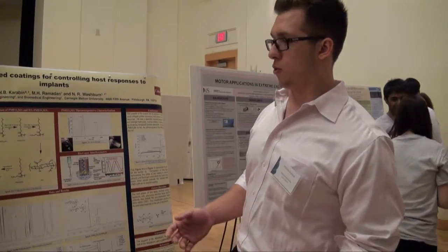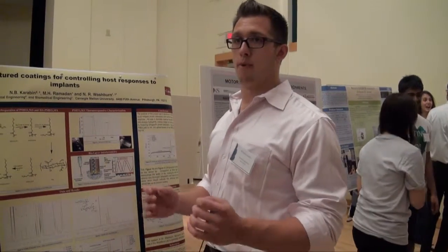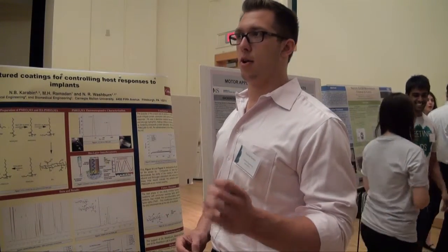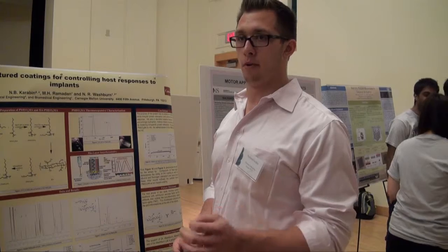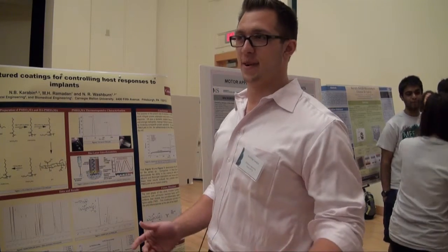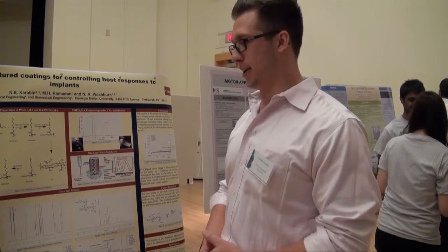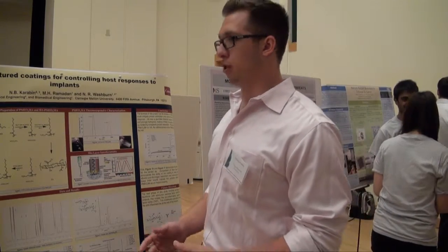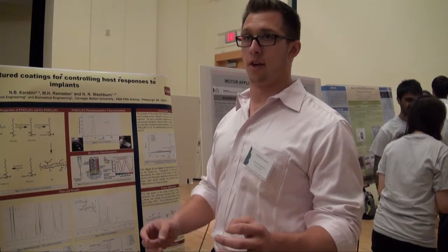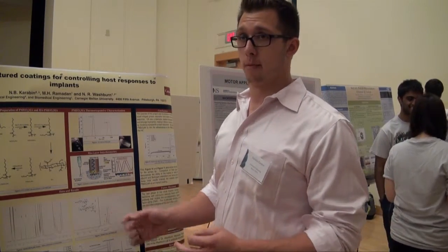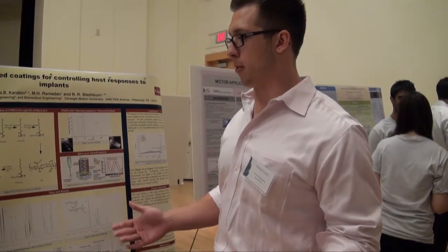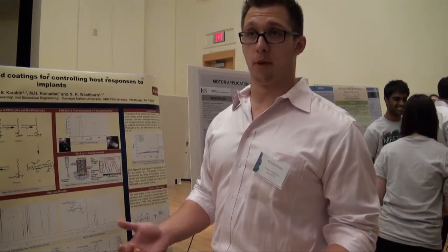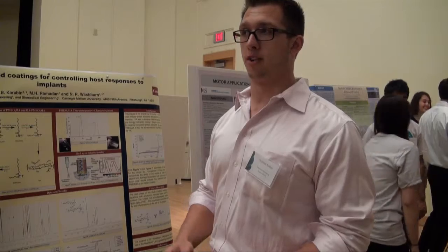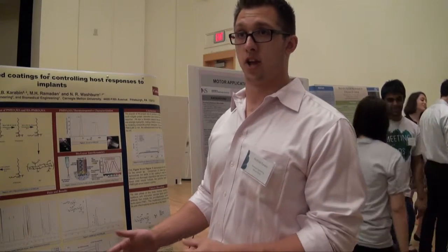So in this project, we are co-grafting poly(diethylene glycol) methyl ether methacrylate to HA. It's kind of a mouthful. And in doing so, we impart some of the characteristics of that polymer to the HA. The polymer is interesting because, number one, it's extremely adhesive, so it's great for making something that's not going to stick to an implant, like HA, stick to it.